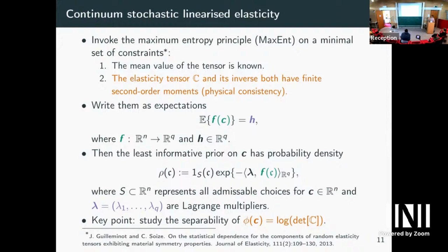And then depending on the symmetry class that you consider, you get simplifications. And the key point is that you study the separability of the map that maps these coefficients to the logarithm of the determinant of the elasticity tensor, of the 6x6 elasticity matrix associated with the elasticity tensor.